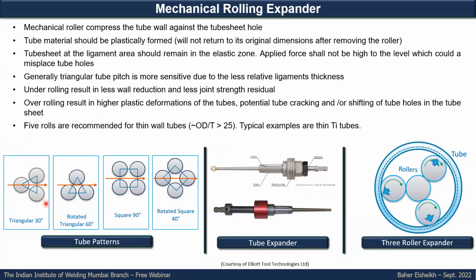You also need to think about the ligament between the tube holes, which is somewhat different between the tube patterns. We have 4 types of tube pattern: triangular, rotated triangular, square, or rotated square. In the square and rotated square, you will find a little bit more material in the ligament area from the tube sheet as compared to the triangular and rotated triangular. That means that under the same maximum force, which can cause some deformation in the hole itself, the deformation in the case of triangular will be less compared to the square or rotated square, assuming the same tube sheet material and the same thickness. So that needs to be considered.